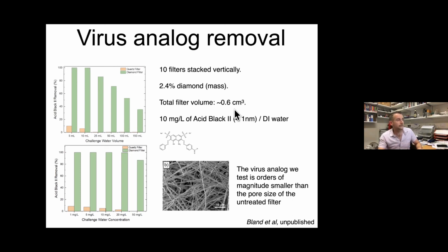We know it's negatively charged, and we just see, can it go through the filter? Well, if it's a quartz filter, it just goes straight through. You can't stop it. But if you reverse the charge, all of a sudden you're able to pull out the acid black 2. It may look like it's deteriorating here, but this is, of course, fouling. We're using very, very high concentrations here. If you do it at virus-relevant concentrations, there's no problem at all.